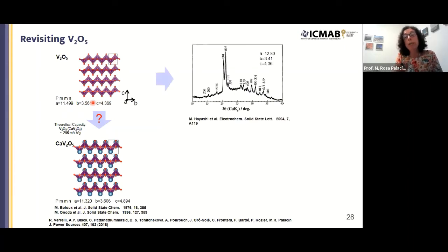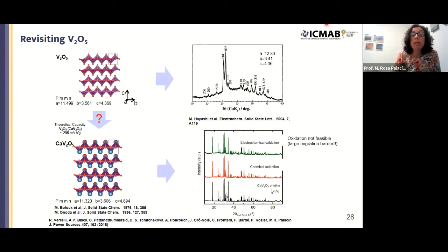And in fact, there had been in the past some reports of potential calcium intercalation in V2O5. There was even an X-ray diffraction pattern given despite no elucidation of the crystal structure. But the thing is that this diffraction pattern has nothing to do with this compound. And in our hands, we were not able to intercalate calcium into V2O5. And we got this pattern when we had water impurities in the electrolyte. So we really believe this is a result of proton intercalation in V2O5.